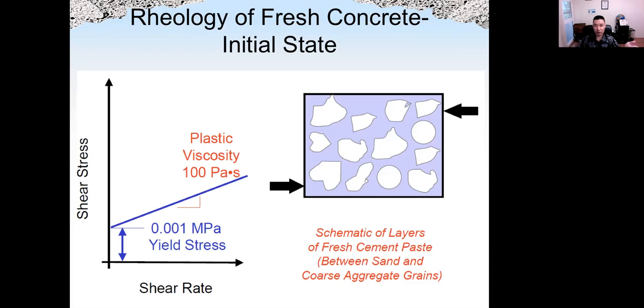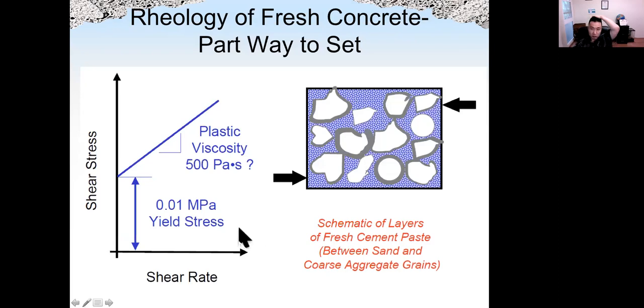And then let's look at the rheology of fresh concrete, from the beginning to initial set time to final set time. Initially, let's say we have a certain amount of yield stress, and the plastic viscosity, which is the slope of the Bingham curve. When concrete hydrates, we have more and more hydration product, and hydration product will try to connect to each other. That will increase both the yield stress and also the plastic viscosity, as you can see here. So the yield stress increases, and the slope of the curve, which is the plastic viscosity, also increases.